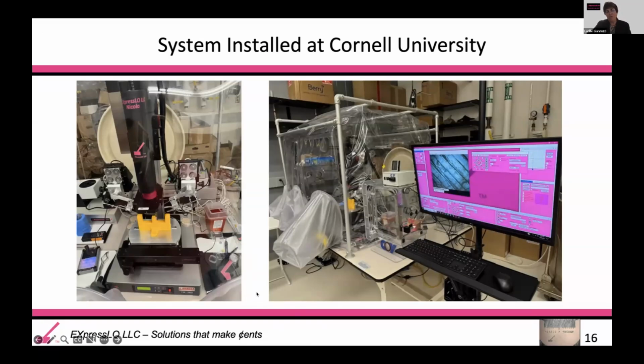But basically, the cryo version of the cryo ex situ lift out solution consists of putting our ambient system, if you will, inside of a glove box where we can contain relative humidity. And because we have since motorized everything about the system, once we load our samples, and I'll show you how we do that, onto the stage of our lift out tool, we can run everything outside of the cryo box remotely.